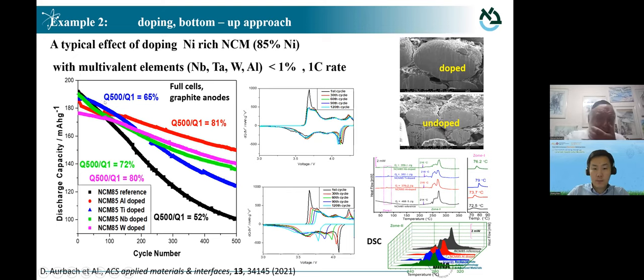And we demonstrate that in some case, for instance, in this case, aluminum shows very good results. We see a nice stabilization. And this stabilization, once we see electrochemical stability, it is reflected by all the other channels that we use. For instance, we have a differential curves. We take the voltage profiles. So you see here the stability over cycling in this chart when we have a good case compared to a problematic case.